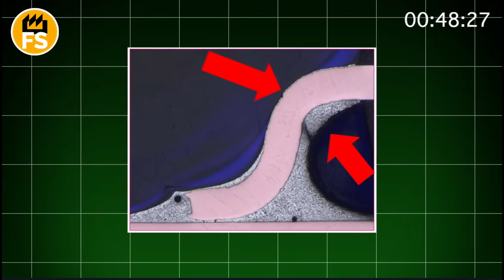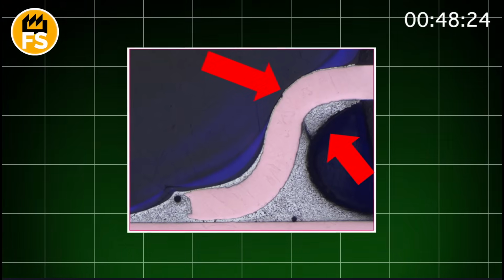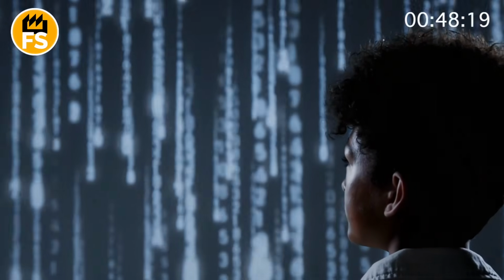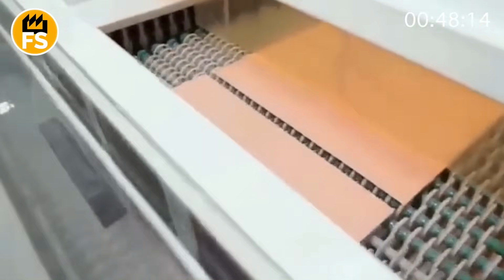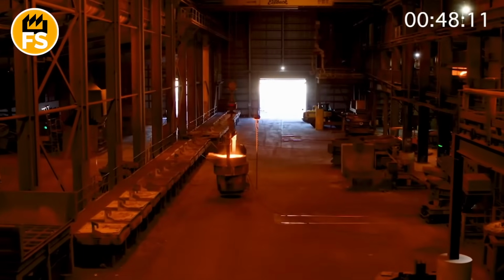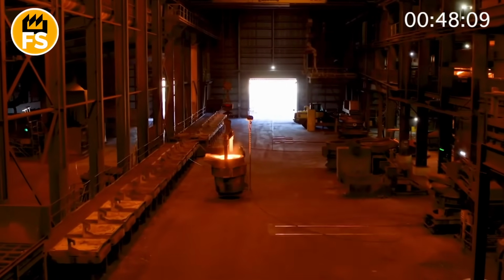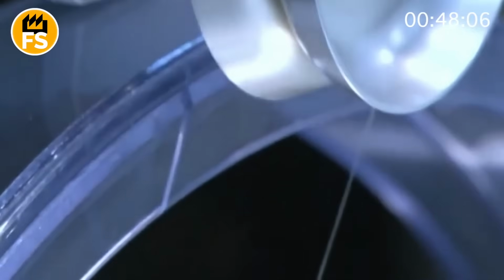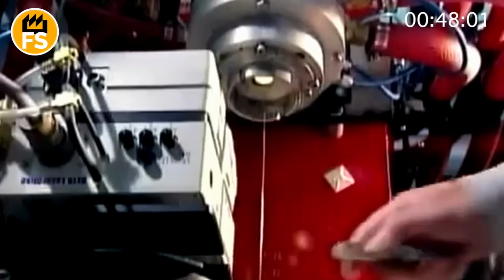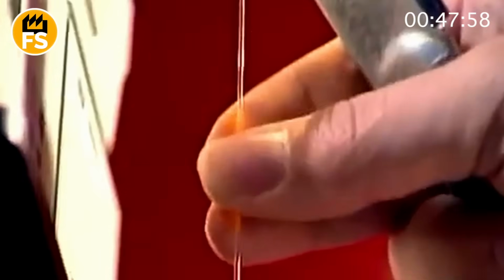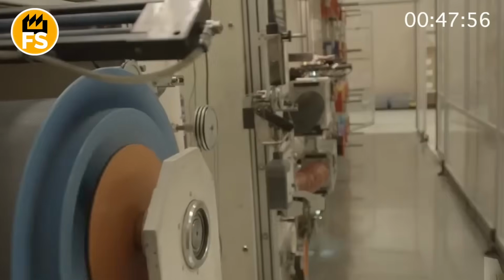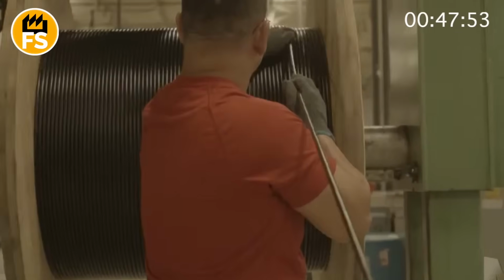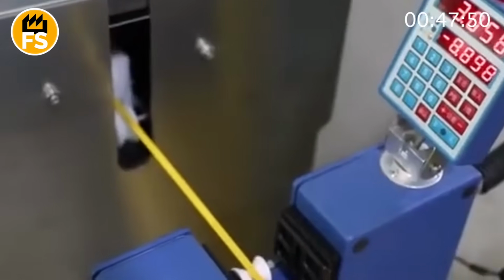The primary coating is a very soft, elastic layer that dampens mechanical shocks and allows the fiber to bend. The secondary coating is harder and more rigid, protecting against external influences, dust, and scratches. These two layers are applied sequentially, one after the other, to provide reliable protection. After applying the liquid coating, the coated fiber passes through special forming rollers. They regulate the thickness and evenness of the layer, pressing the coating uniformly along the entire length of the fiber. These rollers are very precisely calibrated so that the layer is not too thick or thin.